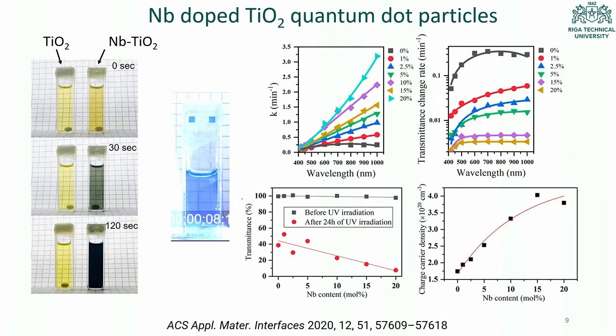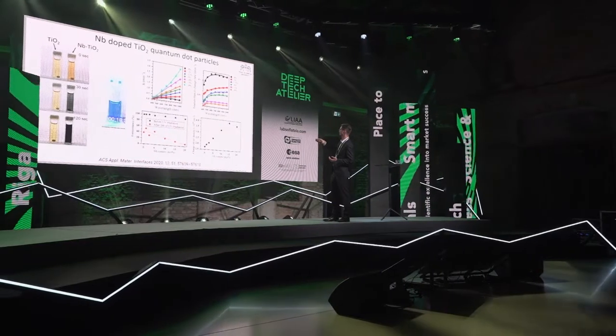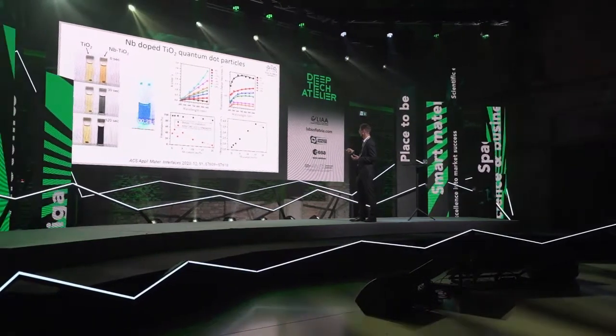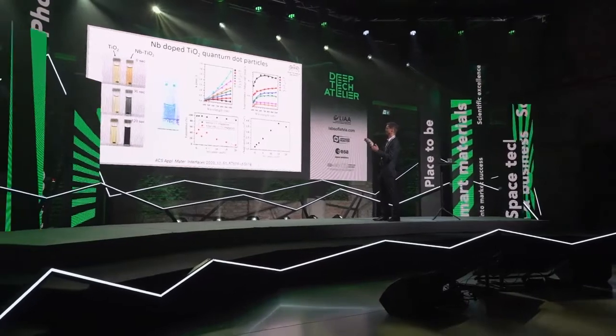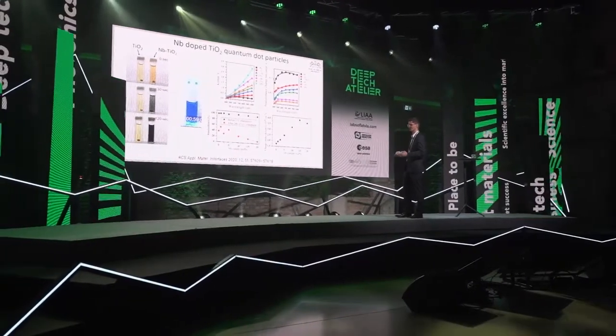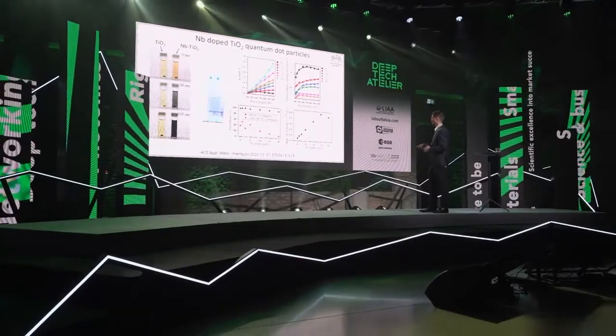Further, after this work was published in 2018, we developed a material which switches much faster. The particles I showed change their color in 1 hour. Now we can do it in 120 seconds. So we tuned our nanoparticles. You probably don't need to pay attention to these graphs, but what they show is that there is an extremely large rate constant in the infrared range, which means we have a strong response for these nanocrystals, especially in the infrared range, exactly what we needed to control infrared light transmittance.